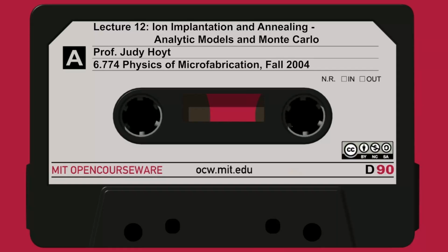So I have a velocity that I can plug into this upper equation, and that is going to end up relating the mass of the ion that makes it through this resolving slit. That mass can then be related to the energy, which is related to the extraction voltage, and the magnet current. So this is usually an electromagnet, which I can adjust the current of. So all you need to do to be sure that you're implanting one particular species is adjust the extraction voltage and adjust the current going to the magnet, and then the only ions that make it are those that you want to implant with the right mass.